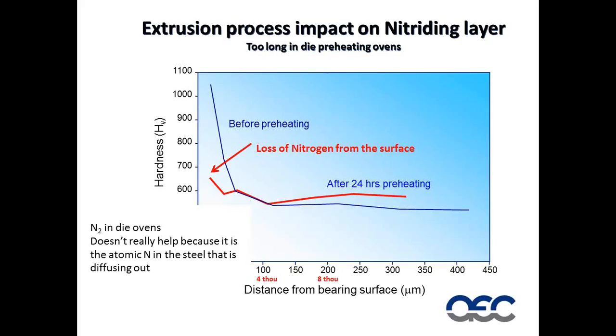So although there is a minor effect of having nitrogen in the die oven to protect the layer, and this is mainly because it eliminates oxygen from the surface as a reactant, it really doesn't totally prevent the loss of nitriding in the die ovens. So you want something that heats the die up quickly and then use the die.